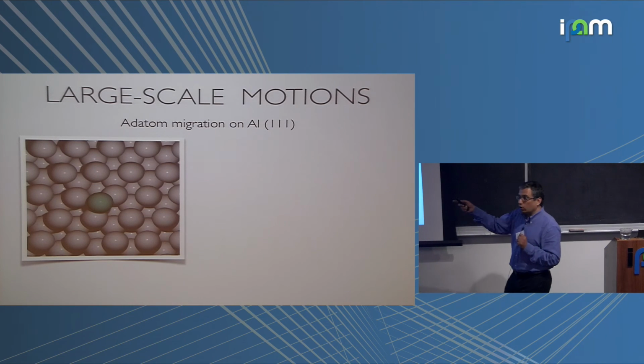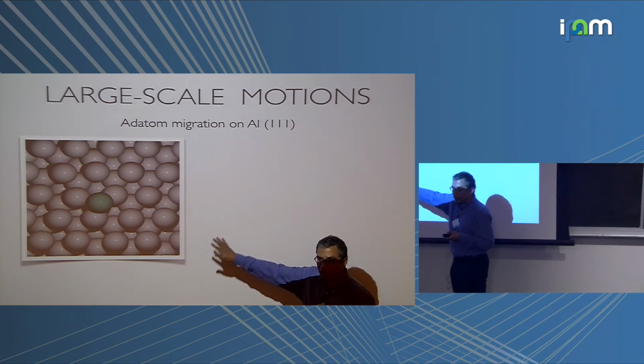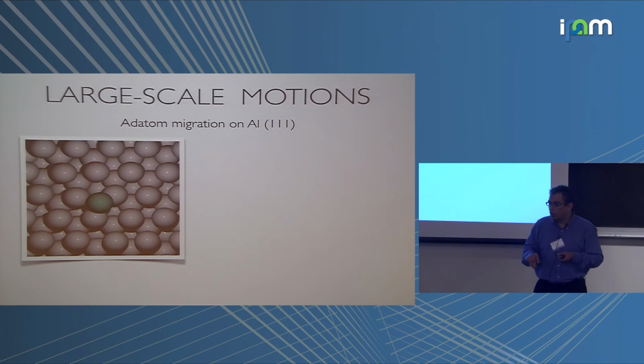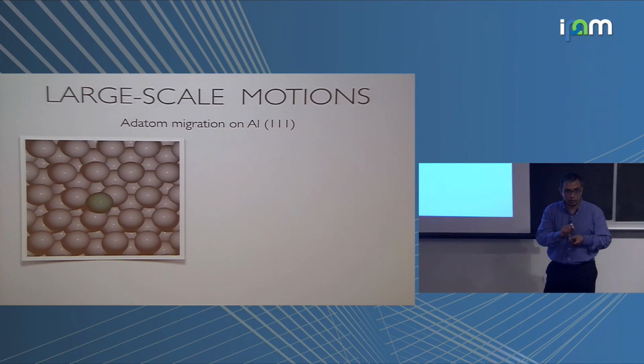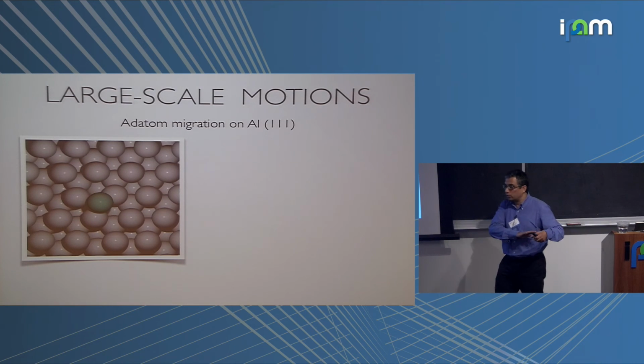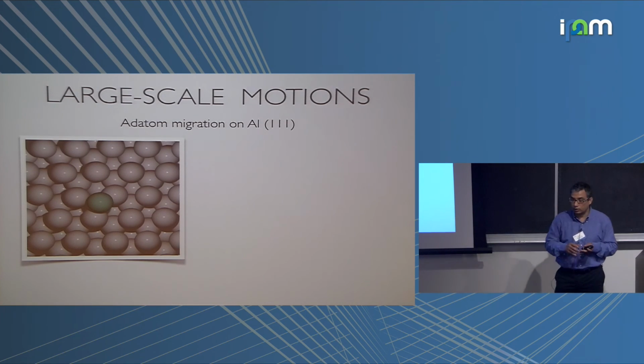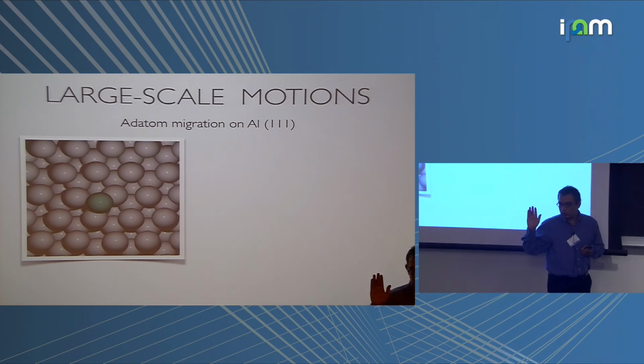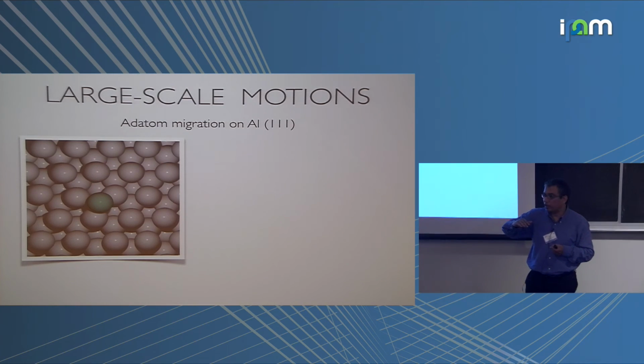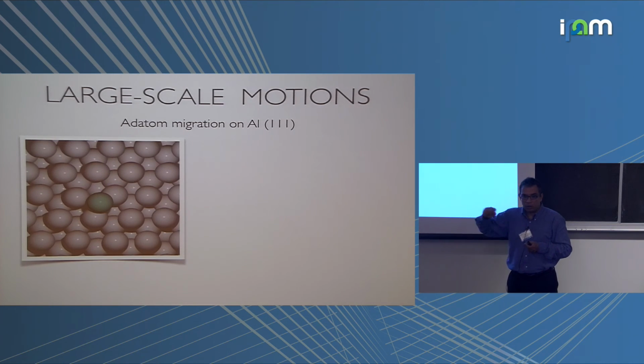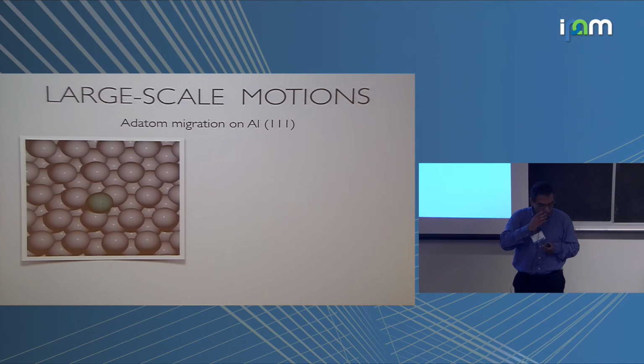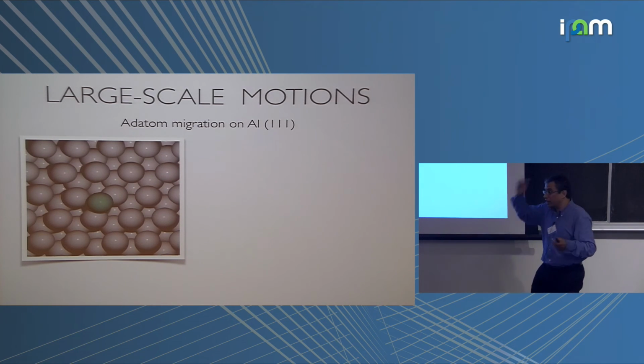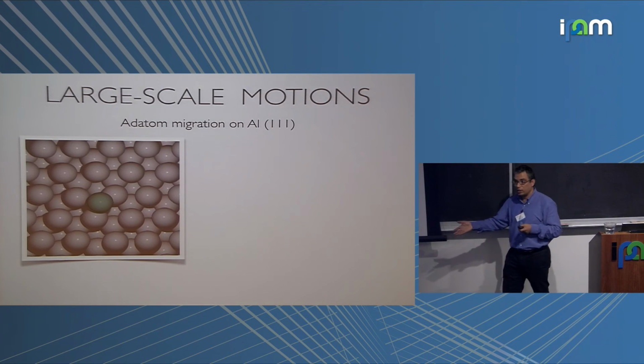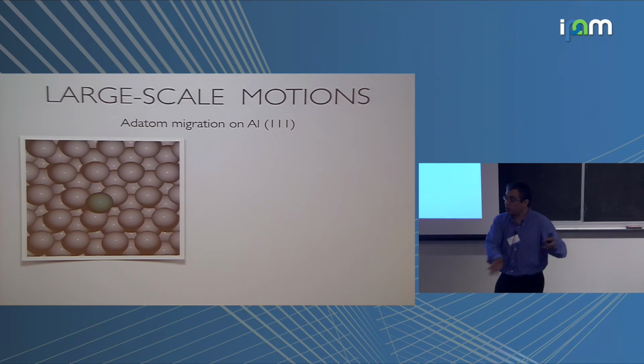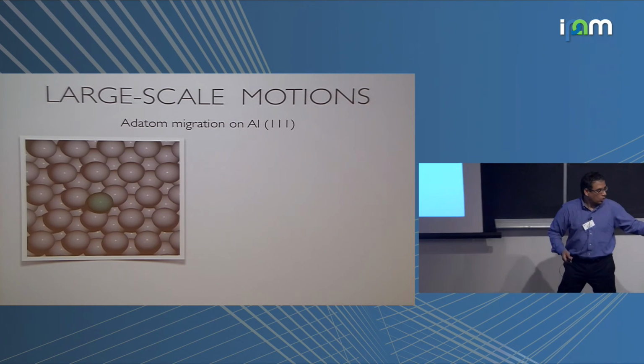Okay, so the question, though, is whether, although we can do the simulation and watch this atom dance around, how accurately are the dynamics captured? Is this force field scheme capturing the physics underlying the dynamics correctly? Well, one way to do that is to do the simulation at various temperatures. For each temperature, we calculate the average hop rate. If you plot the average hop rate versus 1 over temperature, you should get Arrhenius behavior. The slope of that Arrhenius behavior should be the activation barrier, which you can separately calculate. Okay? And we have done that.